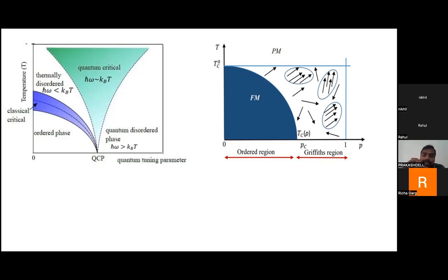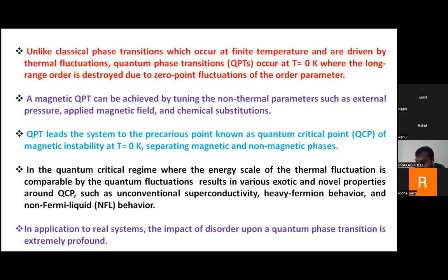But this is very sensitive to the doping concentration and the system symmetry, and it is also prone to the magnetic field. If you apply a strong magnetic field, the paramagnetic contribution to the total magnetization will dominate, and you won't see the presence of the Griffiths phase. But today we are going to discuss how to unambiguously detect it, without getting into the other traditional experiments, let's say specific heat, magnetotransport, resistivity,